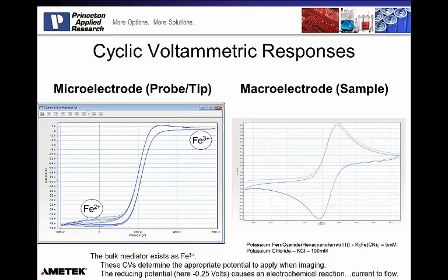However, if I move from the positive potential, if I impose a negative potential or a reducing potential on that platinum disc, I now can force the iron 3 plus to reduce to iron 2 plus. I have current flow. So the primary purpose of this experiment is to decide what potentials I'm going to use in imaging with this probe as I move on to the line scans and area maps. Also, what's nice is you're going to see this is about 41 nanoamps of current at about 200 millivolts. So when I do my approach curves, this experiment happened in a bulk or non-localized way, but when I do my approach curves, that's the level of current that I'm expecting to see in the bulk state before I start getting close to the sample with the probe.